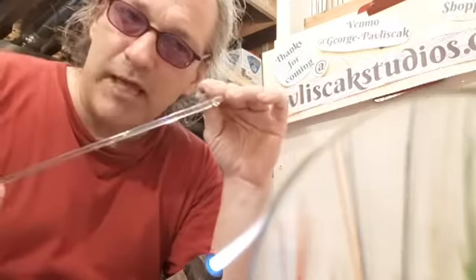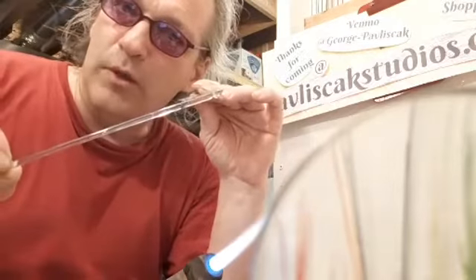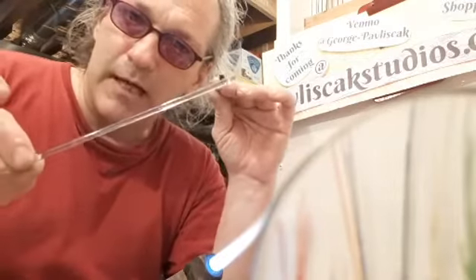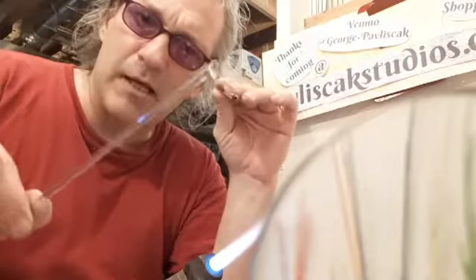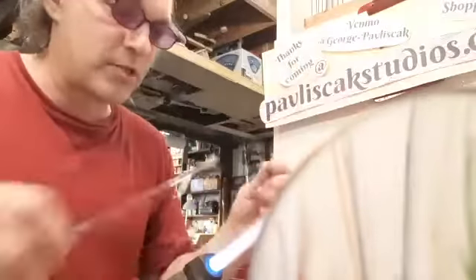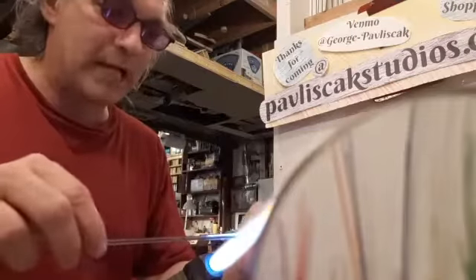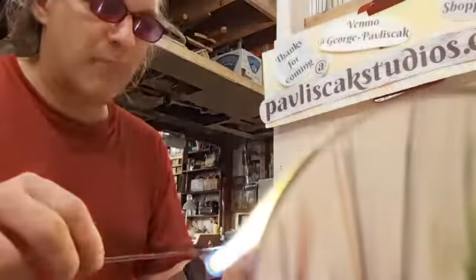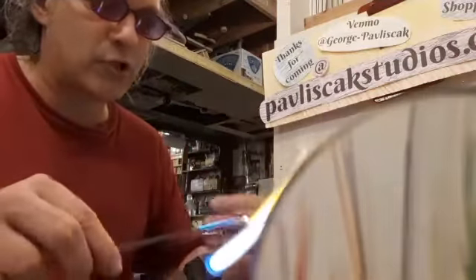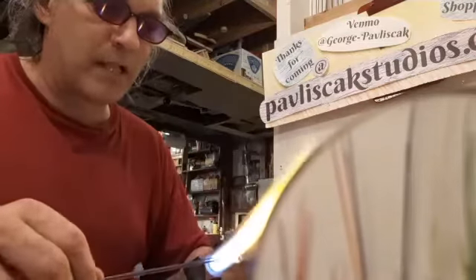These rods generally have little flecks of gold and silver and dichroic, and come out as a kind of a light blue clear. I use this a lot for cores, for handles for holding on to the marble since I can't actually touch them, and that's what I'm going to use for the core of this marble. I'm going to get a gather of this light blue glass that has the same coefficient of expansion and contraction as the rest of my glass colors.